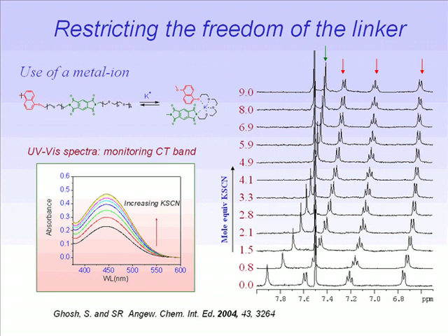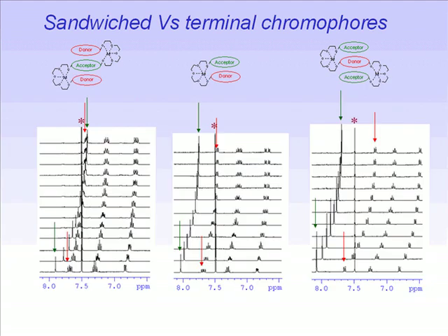Similarly, in NMR spectroscopy, we simply examine the relative position of the peak that belongs to one of these units, and this relative position, in a sense, gives us an idea of the extent of this interaction that has happened in the system. The position turns out to be a mole fraction weighted average of the forms that are free and complex.